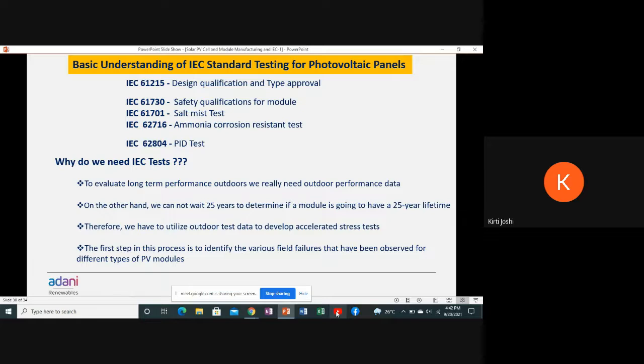At present, module manufacturers give a guarantee that the module degradation after 25 years is about 18%. It means after 25 years, the module will generate power of at least 82% of the module rating. Whatever the rating is for the newly manufactured module, the same module will give a power output of 82% after 25 years. So to assure whether the module will perform as per this guarantee, this qualification is necessary.